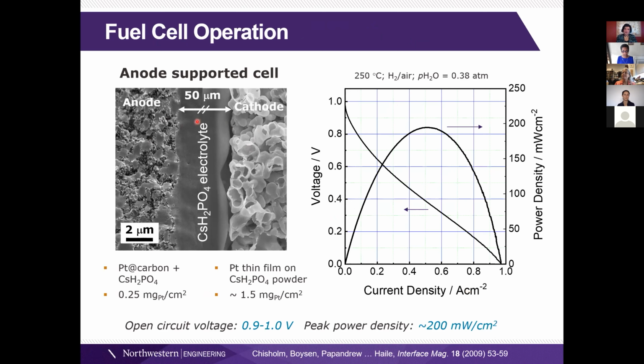This isn't exactly to scale. So this is about a 50 micron electrolyte. I've shrunken that so that we can see the cathode and the anode in it as well. The cathode has the electrolyte material here with platinum covering it to make a good electronic contact and also good proton contact. And then it's porous so that the oxygen can make its way in.